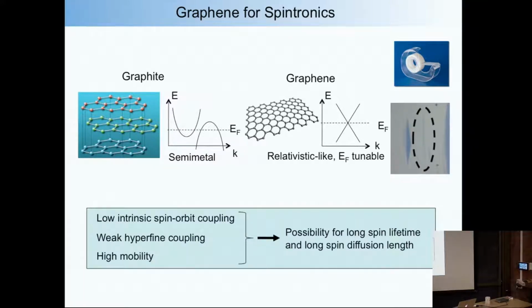of graphene. And why it's interesting for spintronics is that because it's made out of carbon, you have a low intrinsic spin orbit coupling, and also because most carbon doesn't have nuclear spins, and also because these are pi orbitals, so you don't have contact hyperfine interaction, your hyperfine coupling will be very weak. So the interaction with nuclear spins is very small. And typically that's a good thing for having spins live a long time. And also the material has high mobility. And so you put these together, there's a possibility for a very long spin lifetime and also long spin diffusion lengths. Okay, so this is sort of the original motivation. Let's try this material out.